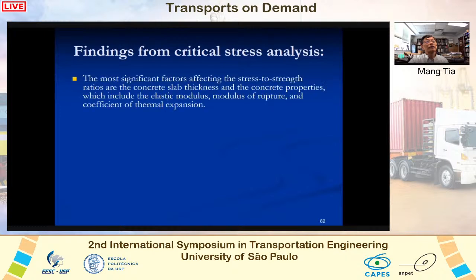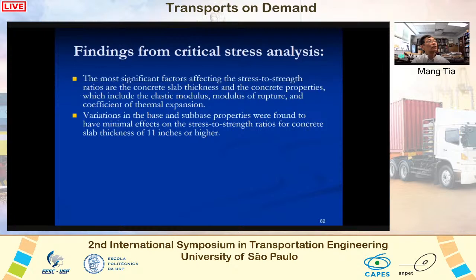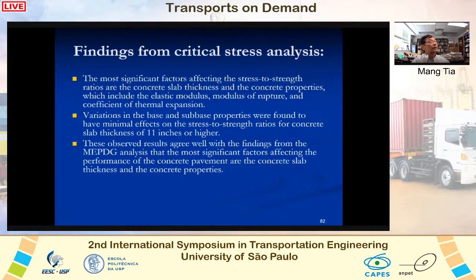Okay, here's a summary of the findings from the critical stress analysis. The most significant factors affecting stress to strength ratio are the concrete slab thickness and the concrete properties, which include the elastic modulus, modulus of rupture, and coefficient of thermal expansion. Variations in the base and sub-base properties were found to have minimal effects on the stress to strength ratio for concrete slab thickness of 11 inches or higher. These observed results agree well with the findings from the MEPDG analysis.